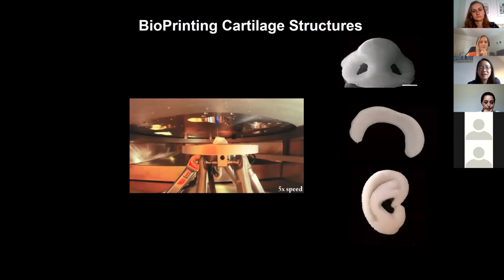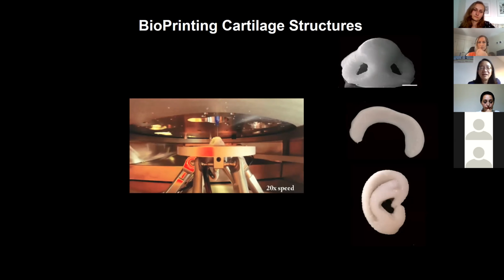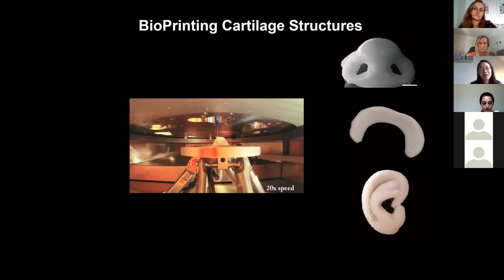As it turns out, the big challenge in bioprinting, at least cartilage, was to get the flow properties of the materials that we're printing to be right. So what you can see in this video is a material, we call it a bioink. And this material's rheological properties have been engineered so that the material can flow through the nozzle during the printing process, but then stops flowing after the printing has stopped. So you can see this nose structure. It's a paste. It hasn't been cross-linked yet, but it's keeping its shape. It's not that you print and then the fidelity of the print becomes less and less. And so this actually turned out to be a material science, material flow problem that we were working on.